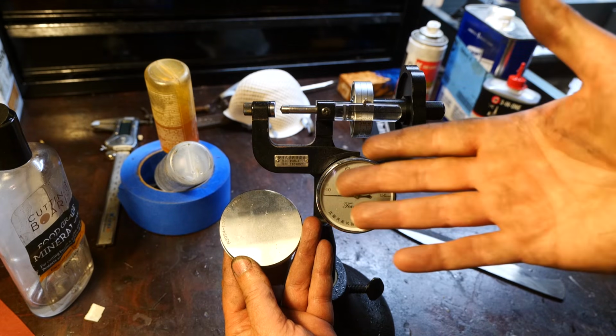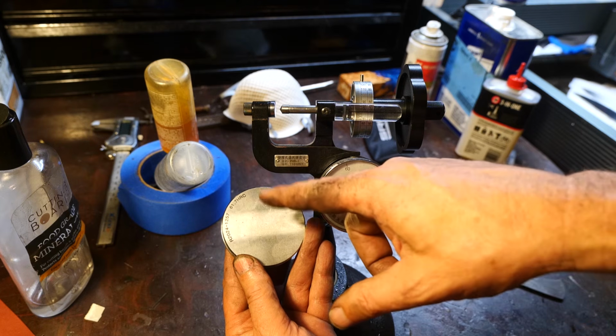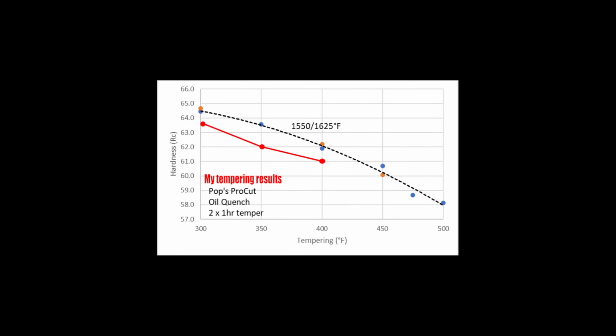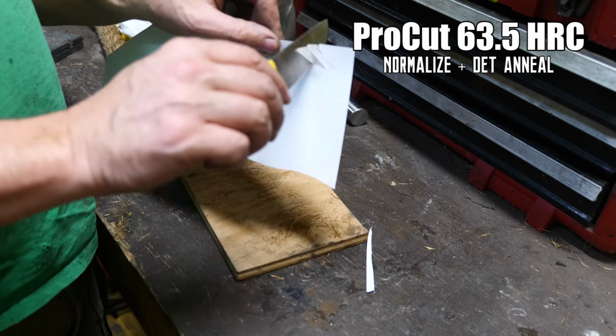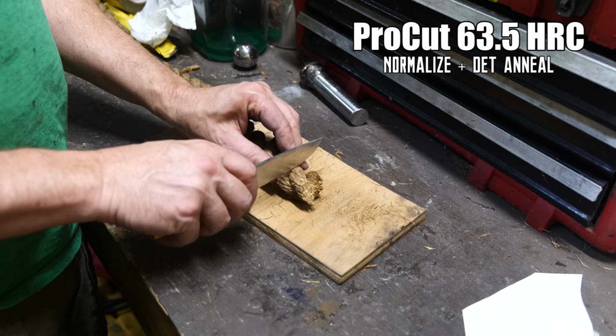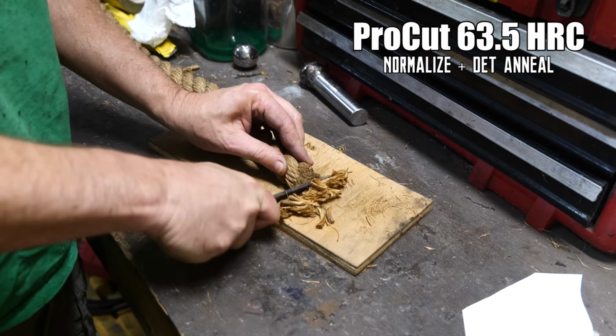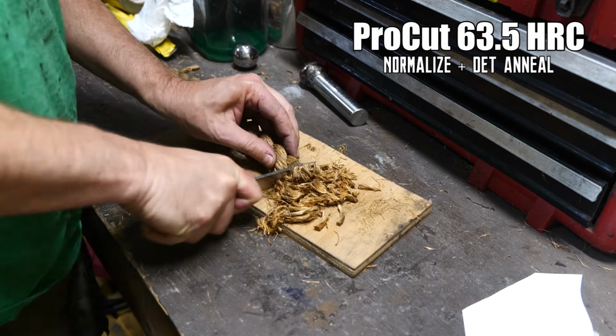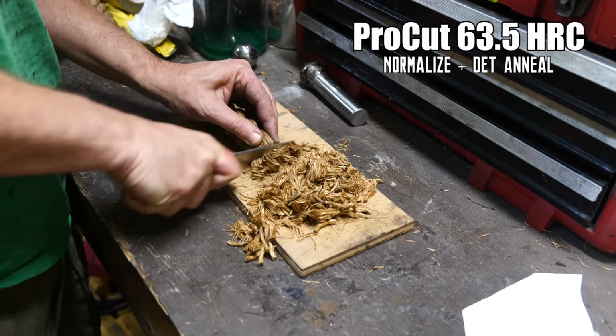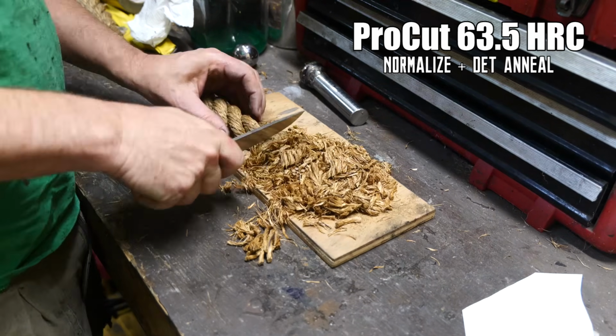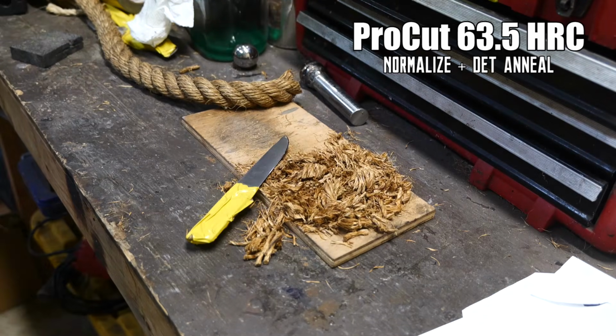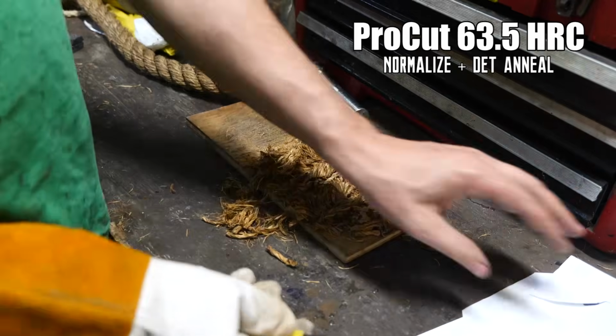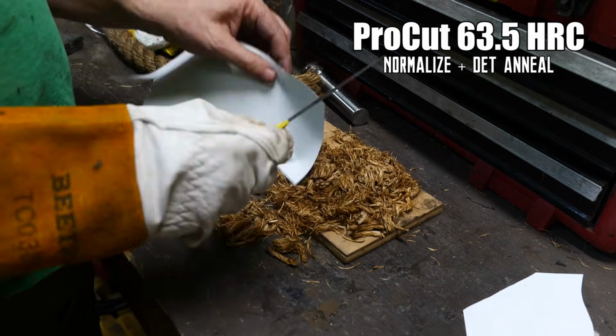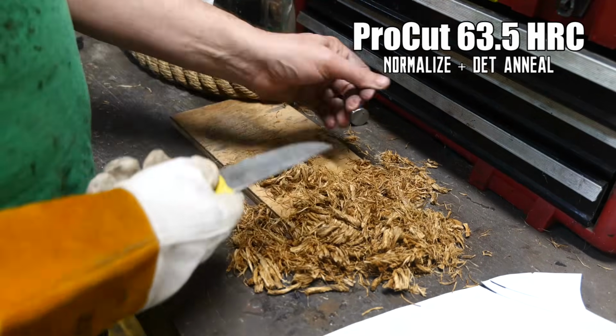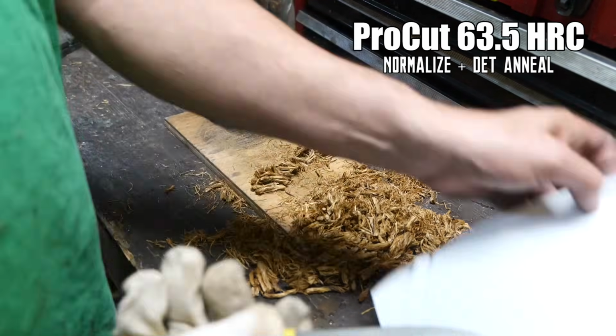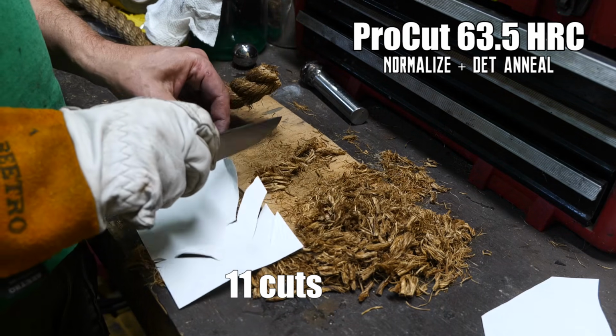And by the way, this does come with a calibration block. You guys don't see me use it, but I calibrate it before each experiment. So after a full heat treatment, this temper curve is a lot closer to what's expected. Let's put it through rope and see if we get a different result here at 63.5 HRC. I mean, believe it or not, it's still the same performance.